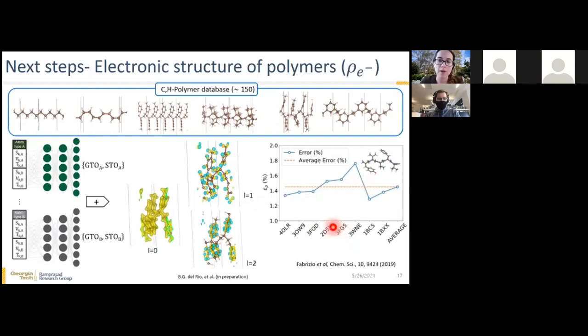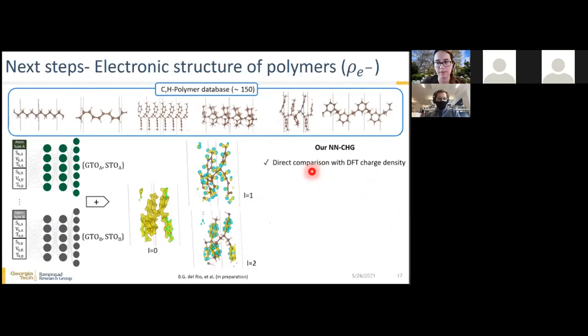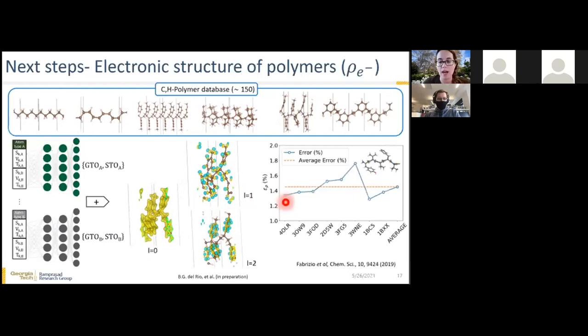Now, in comparison, our model compares directly to the DFT density. That's one thing when doing the prediction and the training. When doing the training of our model, the target value is directly the DFT density, not the already decomposed density. And also, it does not require a previous decomposition or, in fact, any previously created basis function, as the model is going to learn the optimal basis function. Also, our model only employs the valence density, and the error percentage that we get is around 0.9 and 1.3, which is similar to the values that we were seeing here. But then again, theirs is using also the core electrons. So if they were to just use the valence electrons, probably it would be much higher.